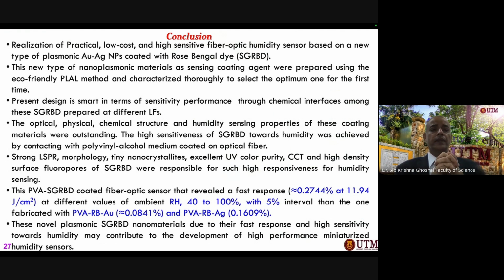So this new type of nanoplasmonics-based material as sensing coating agents can be prepared by the PLAL technique. And as I told you, because the PLAL technique has a lot of parameter space, customization of the electronic and optical densities of states is possible in a wide range of systems, where you can play with the morphology, the shape, the geometry of the nanoparticle, pH, laser energy, laser pulse duration, and many other things. So the optical, physical, chemical structures and humidity sensing properties of these coating materials can be outstanding, and the high sensitivity of this rose Bengal dye coated nanoparticle. Rose Bengal dye is a very interesting material, and a lot of work has been started with this kind of dye molecules. This dye molecule is very promising for sensing technology.